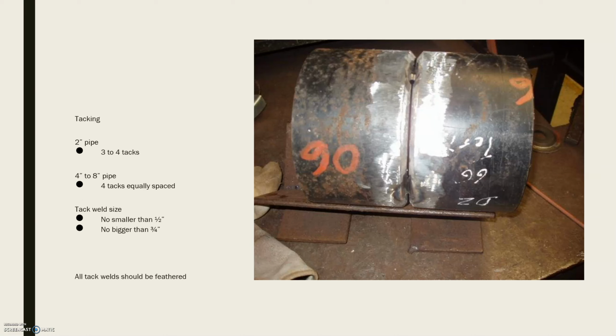Lately, tacking is the main cause of failures for the Class A pressure test. Tacks must be equally spaced. 1/2 inch to 3/4 is a good size to shoot for. Most pressure tests will fail you for going over a 3/4 inch tack size. If you have a tack size under 1/2 inch, most likely it's going to crack.